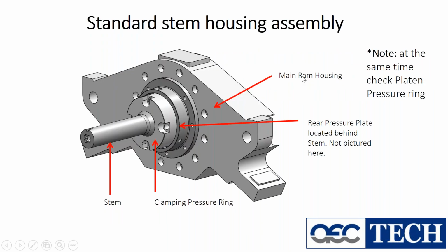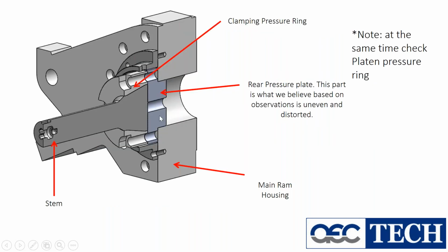So if we look at where that is located, I'm going to just go through that. But quickly, one other thing I wanted to put in here is at the same time, if you're pulling the stem and the holder and the stem pressure plate, which is located back in behind the stem, check the platen pressure ring. That's the pressure ring that is located in the platen. Do the same thing. Check that for flatness. Make sure it's square. Make sure that it's true. Because if not, now that die has the opportunity to pivot. And under pressure, it'll pivot.